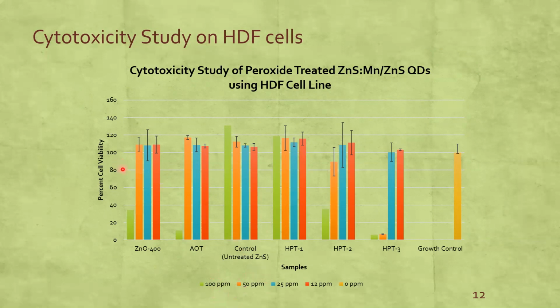Generally, the material is considered safe if they show above 80% viable cells. So we see that HPT1 and control didn't show cytotoxicity up to the highest concentration tested, and HPT2 up to 50 ppm retains 80% viable cells and appears to be non-toxic to HDF cells. HPT3 is the most cytotoxic among them, so this is not a preferred system for field trial despite its antimicrobial efficacy. Also, it has no fluorescence.